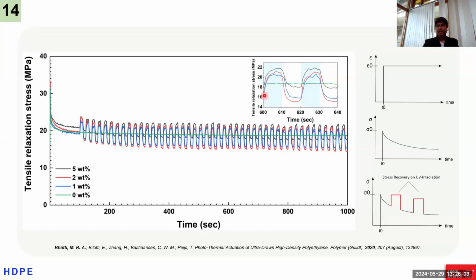As you can observe over here, the blue region represents the illumination state and the white region represents the non-illuminating state. So it's just a matter of seconds before the response gets back to its original position, meaning the films get back to their normal position. But if we cross the alpha relaxation temperature, the films do not get back to their normal position, because we are now crossing the elastic region of the films. The tie molecules get relaxed and are like an amorphous region, which can go either way. And if we increase the temperature too much, the film might even melt.